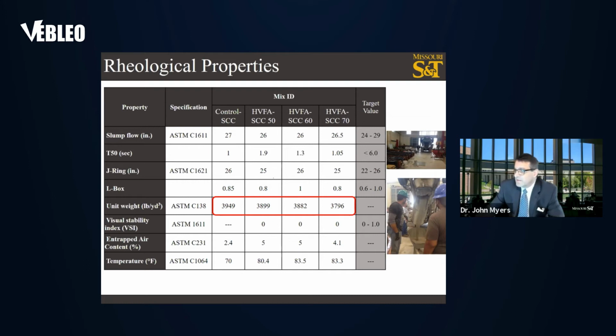And you can see in this table how they compare. Also notice that the unit weight, as we add more fly ash, due to the lower specific gravity of the fly ash relative to the Portland cement, reduces the weight or the unit weight of the mix design.